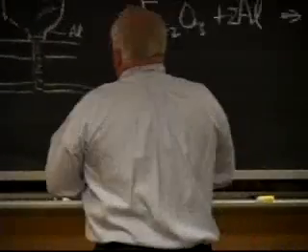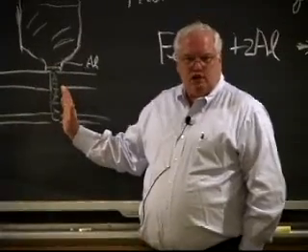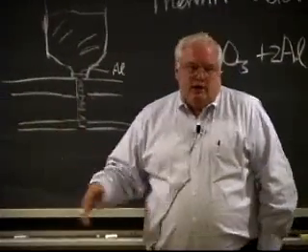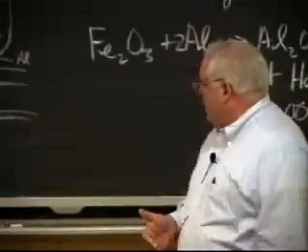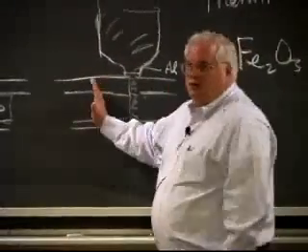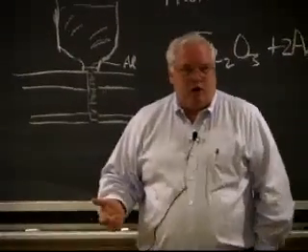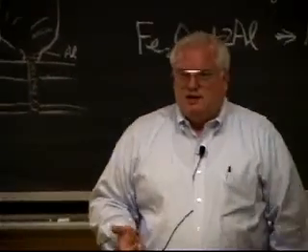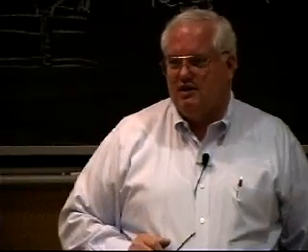The problem is you get about 50% defective welds where you don't get good fusion on one side or the other. So when you have 50% defective welds, it means you got to cut it out. If you cut it out, you got to put 2 welds in the part that you cut it out, and the 2 welds you put in each have a 50% probability of having a defect. And so you can see that this is a slowly converging series of getting a decent weld.